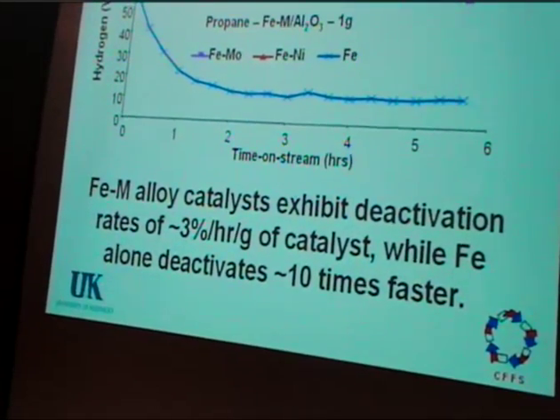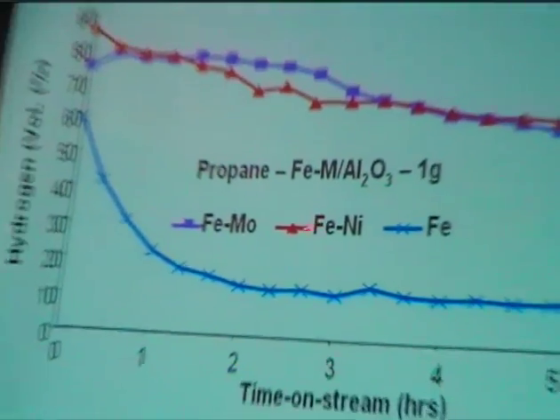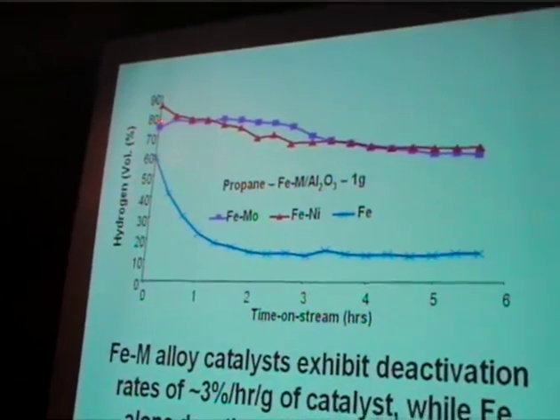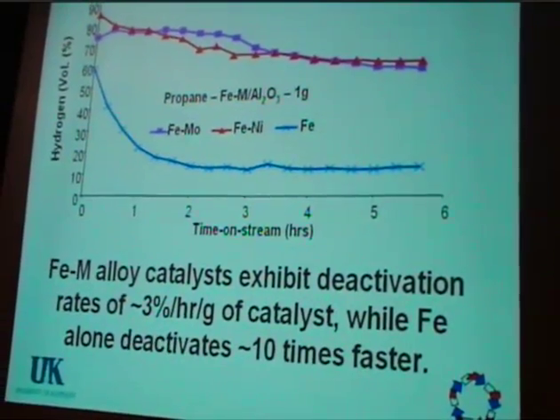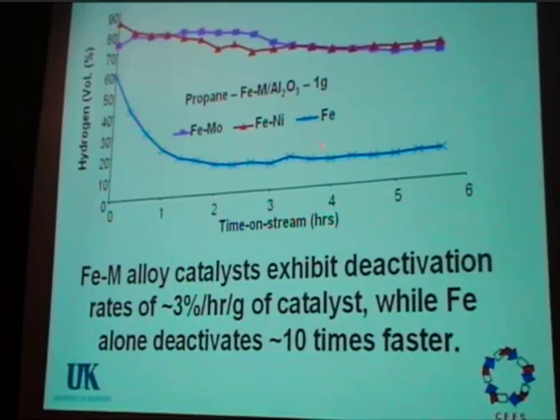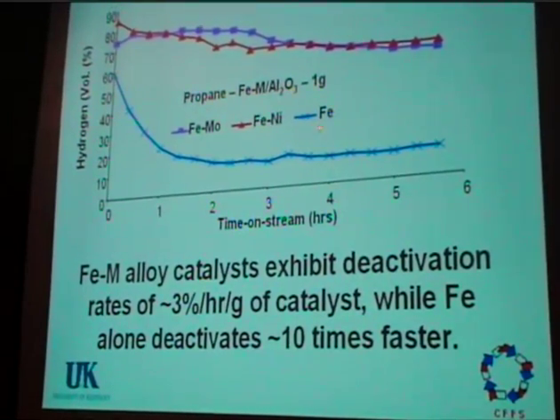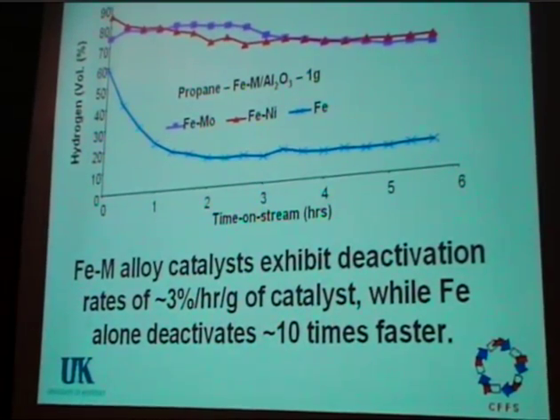nanotubes. In terms of time on stream behavior, here we show propane and 2 of the catalysts. The results are pretty active for propane, ethane, and methane. The decrease in activity is about 3% per hour per gram of catalyst. And just for comparison, we showed one with just the iron catalyst, just iron on aluminum, rather than the alloys. And you can see that that decreases in activity about 10 times faster.